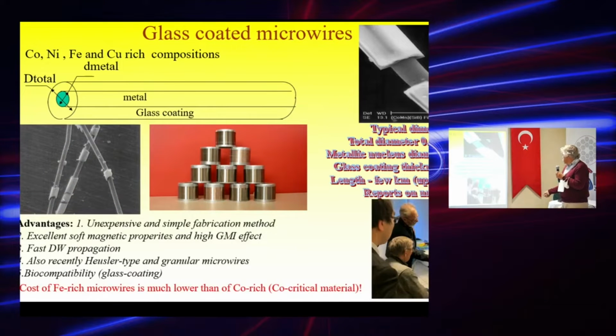And here you can see the most recent setup which we have in our spin-off company in San Sebastian. These materials present different features quite attractive for applications. For example, they can present fast domain wall propagation, excellent magnetic softness, and a high magnetic impedance effect. They are mostly biocompatible because of the glass coating, because glass is biocompatible with the human body, so they could be useful for medical applications. Recently we have even tried to produce crystalline materials, Heusler type alloys or with granular structure, and this could be useful for different applications.